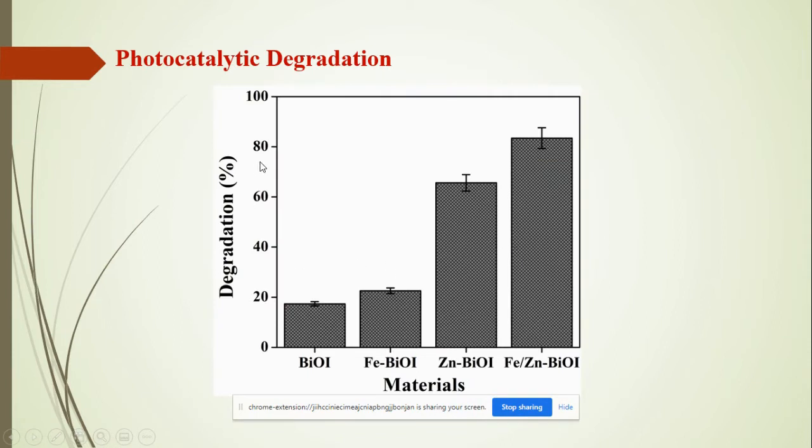We performed different kinds of experiments using tetracycline. Here we have taken concentrations of 1 to 10 ppm of tetracycline, and we used different kinds of semiconductor material, metal doped and without metal doping, to check the degradation of tetracycline in water solution. Here we have used bismuth oxyiodide, iron based bismuth oxyiodide, zinc based bismuth oxyiodide, and iron and zinc bimetallic bismuth oxyiodide. And you can see here the maximum degradation was observed using iron and zinc based bismuth oxyiodide microsphere, which is around 86% at 10 ppm of concentration.